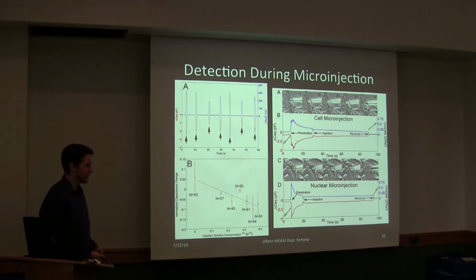Another very nice thing about this technique is that the nuclear membrane acts as another membrane in series, and so we can actually determine whether we're injecting into the cytoplasm or nucleus based on the magnitude of the signal change. So we found that on average the injection into the nucleus gave about 1.5 times greater signal change compared to the cytoplasm. So that gives us another tool we can work with for feedback.